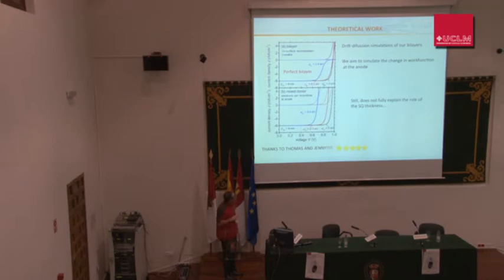Okay? And then we went to physics. Jenny Nelson and Thomas Kirchartz at Imperial College did some modeling for us, trying to explain if what we see is also a change in the work function, because we must make sure that we are not changing the potential at the contact. And they did that, and of course, in a perfect bilayer, it doesn't work. You can see here this A shape. We never saw A shapes, so it cannot be a perfect bilayer, so we were right. But it also doesn't explain the case of a fully mixed donor, because it doesn't have the same trend. The voltage keeps increasing. And we see that after a while, the voltage doesn't increase anymore.